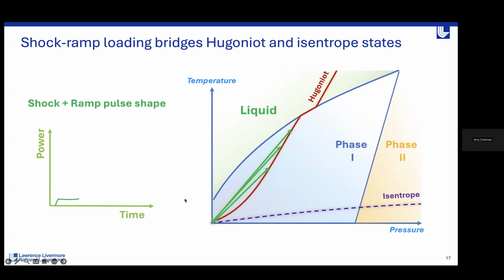If we have a low step, we can get ourselves to a lower point on the Hugoniot. If we put a bit more energy in this first shock step, then we can get ourselves to a higher point. And then the pulse shape following this initial shock has a gradual curving slope and intensity more reminiscent of ramp compression.